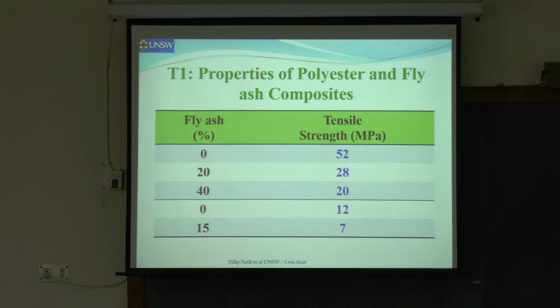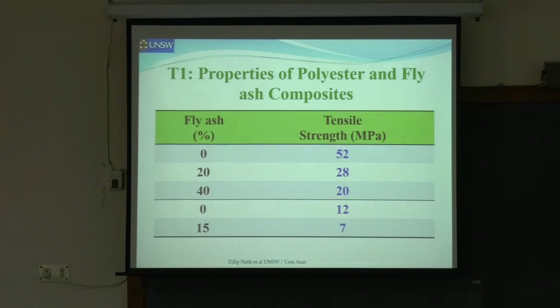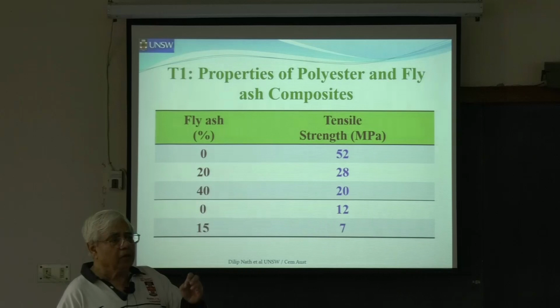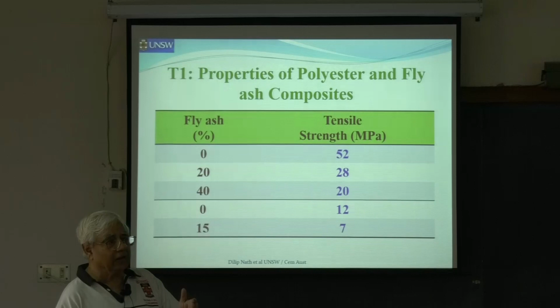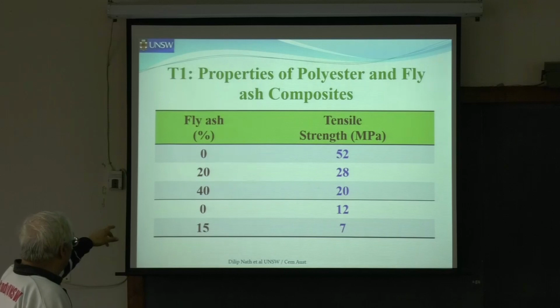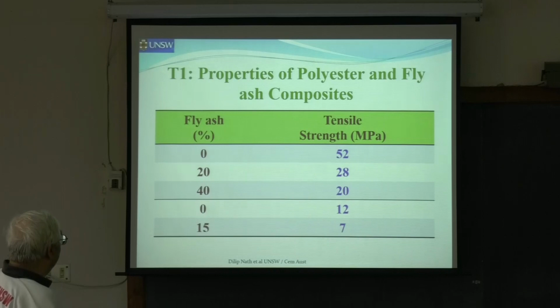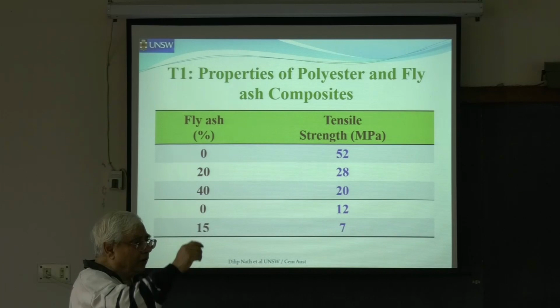Now, properties of polyester and fly ash composites. What people have found is that if you put more and more fly ash in, again, this is not his work, the strength can go down. The reason for that, as I was saying yesterday, is that if there is a discontinuity, with spherical particles, it gives a stress concentration of 3. Which means, without any fly ash, if the tensile strength is 52, and when you put in 20% it's 28, that means there is stress concentration there, and that is reducing the strength, all right?